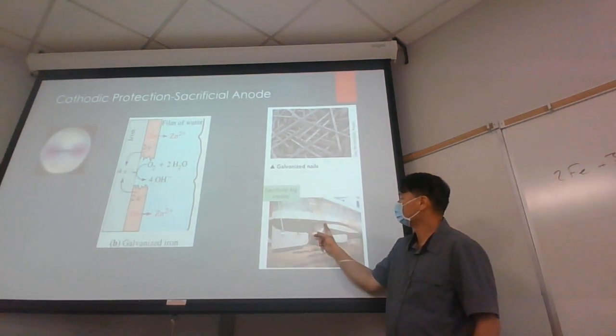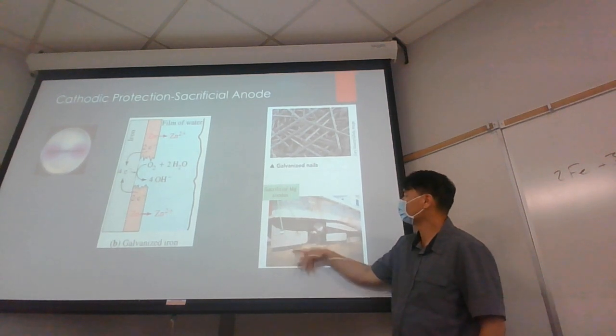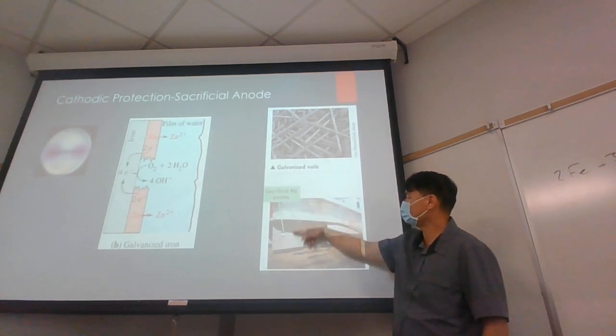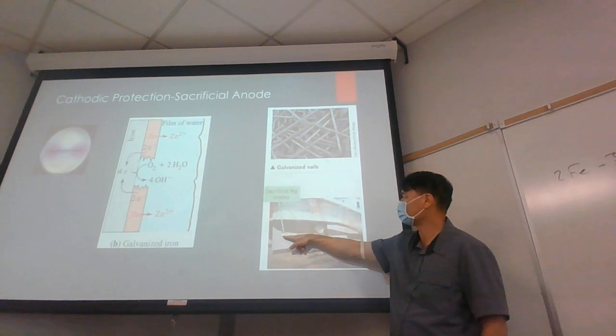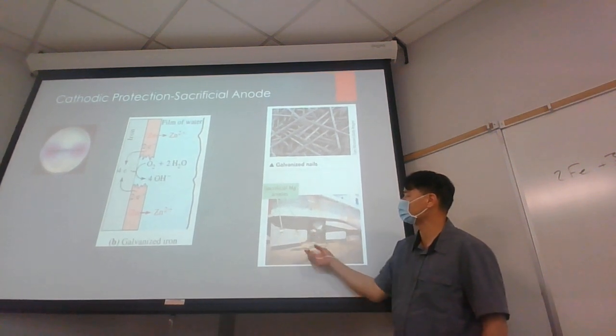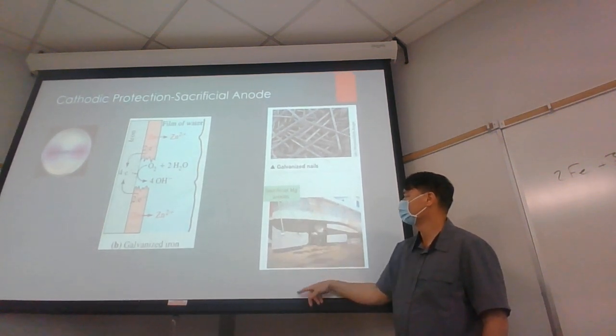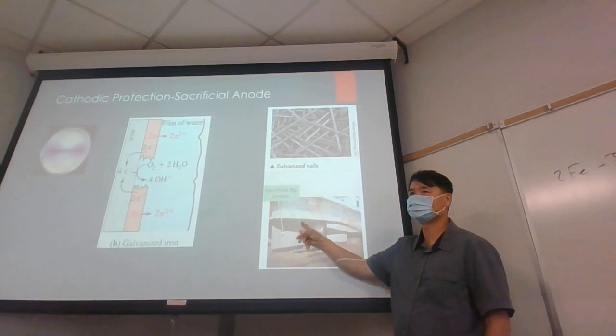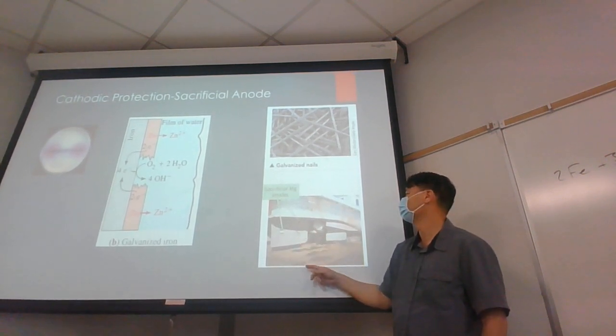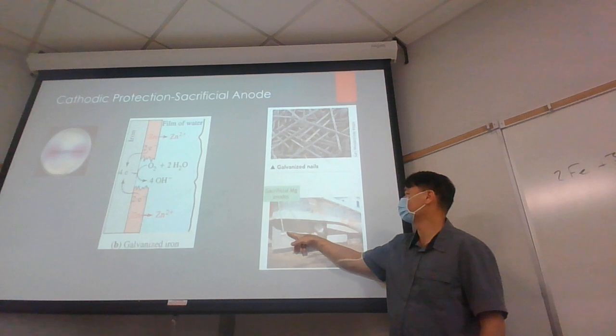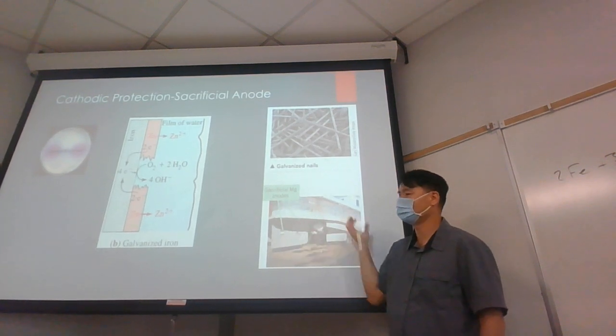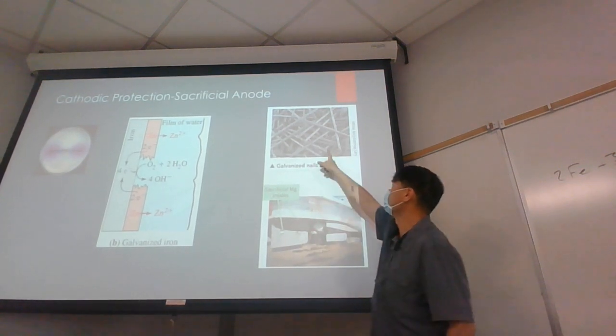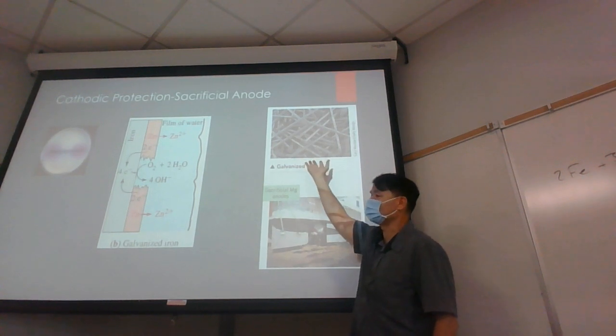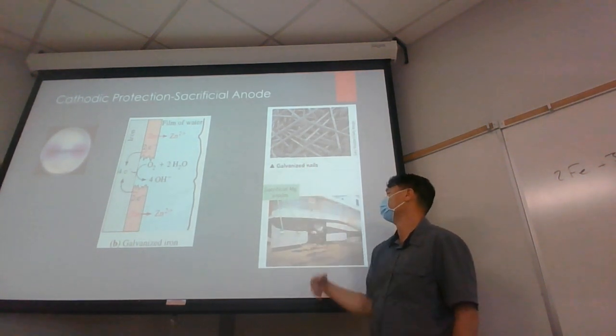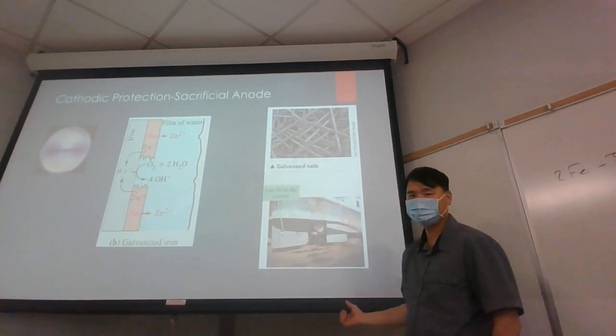Here on boats, they don't dip it in zinc. Instead, they use sacrificial magnesium anodes, so there's just magnesium attached to it. Magnesium has a higher oxidation potential than steel, and so the magnesium is oxidized first. It sits in salt water. And so the sacrificial anodes are replaceable because they're going to be eaten away. Eventually all the zinc will get eaten away, and then the iron will start to rust. When that happens, then we'll lose the nail.